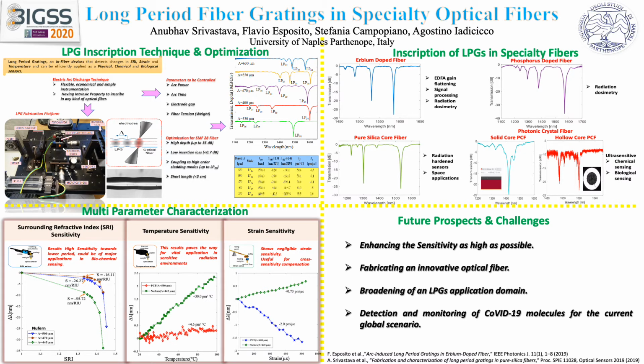The typical values of the splicer parameters for producing an effective discharge are an arc power in the range of 1 to 20 steps and a duration of 200 to 800 milliseconds. Generally, a constant force of about 120 millinewton was applied to the fiber by using a 12-gram weight and a high precision pulley.